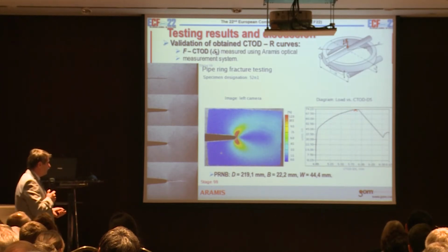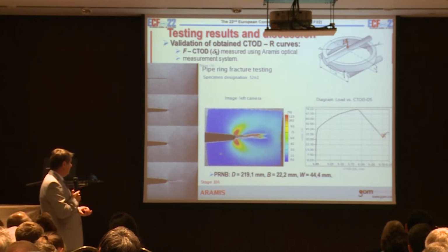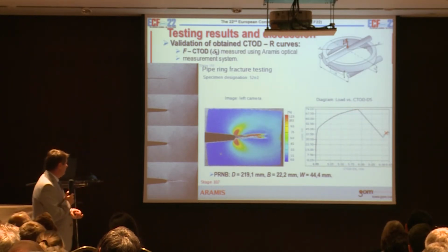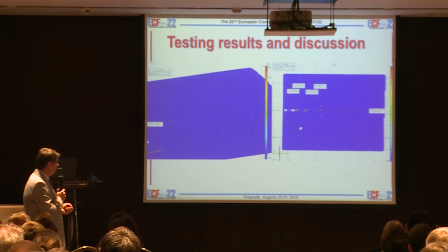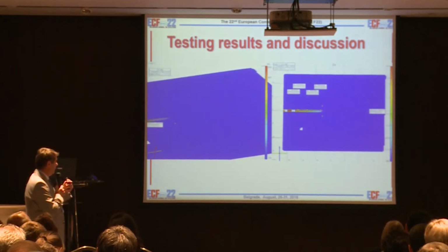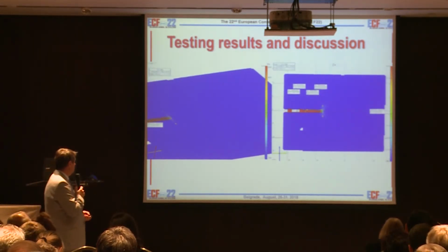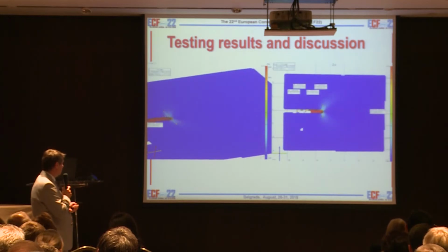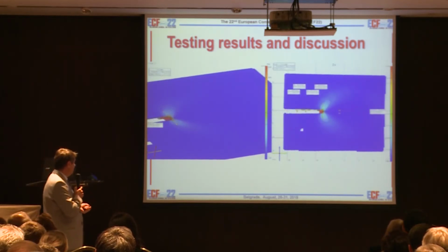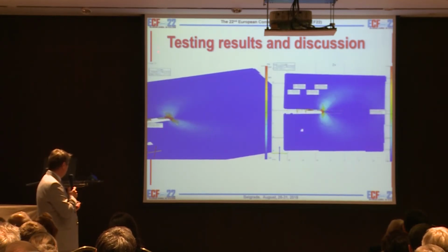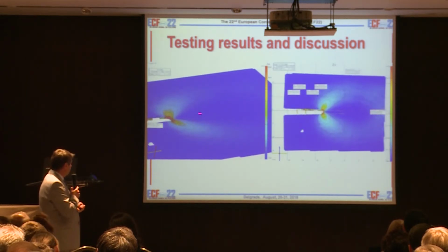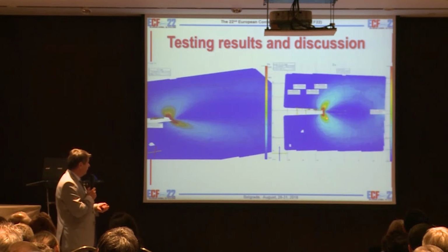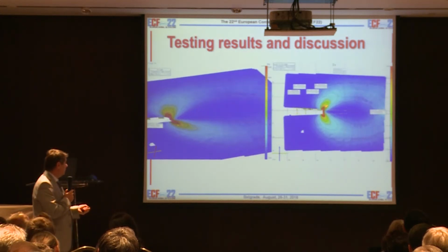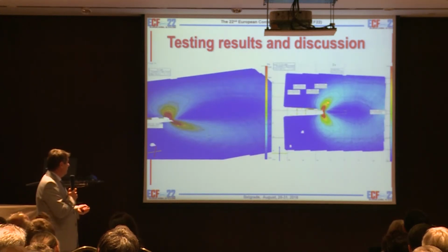So, of course, this is the last point on the curve. Then we stop the test, and we can also measure the crack extension and do the post-test analysis in order to determine the curve. Here you can see these 2 points at 5 millimeters displacement. Here is the plan view, and here is the side view.